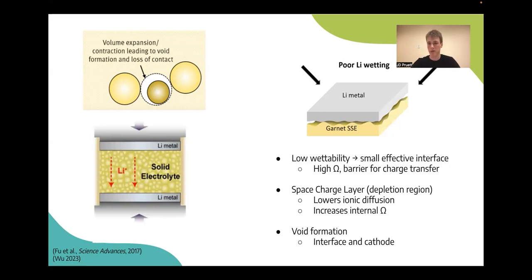Now, one way that we've dealt with this so far is we just apply pressure to the whole battery stack. So we effectively squeeze it. And this can prevent this wettability issue, right? You can imagine if you really squeeze those two plates of metal together, you're going to have better contact, which can lower resistance and improve the overall efficiency of the battery.